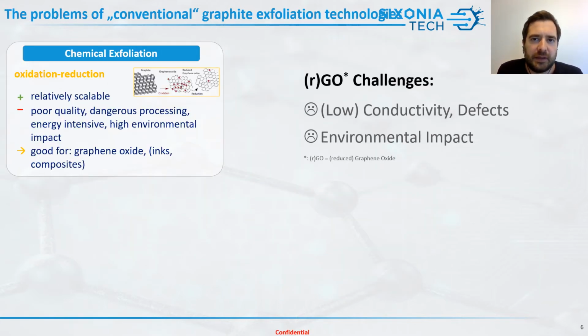So what we have, on the one hand, is graphene oxide as a large scale production method that is really performed on the ton scale, and it's a scalable method and good for various things. Graphene oxide is a really nice material to play with and to functionalize, for example. It can be easily modified due to the plethora of functional groups that are already present. But the fundamental challenge is that the process is quite environmentally dangerous, I would say. You produce a lot of wastewater and heavy metal residues that you need to take care of. And eventually the material that you get is over-oxidized. You produce so many defects that you get a processable material, but it's not conductive anymore. So this can be a problem for your application.